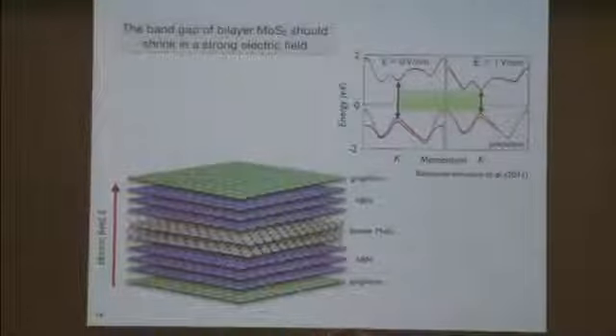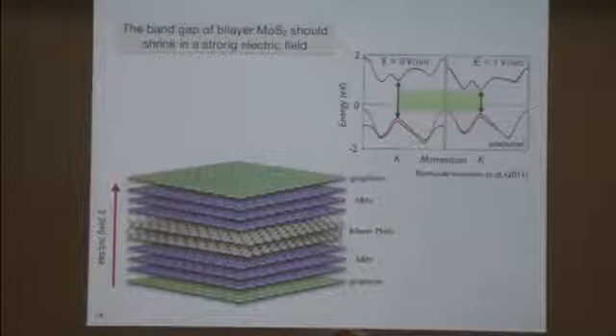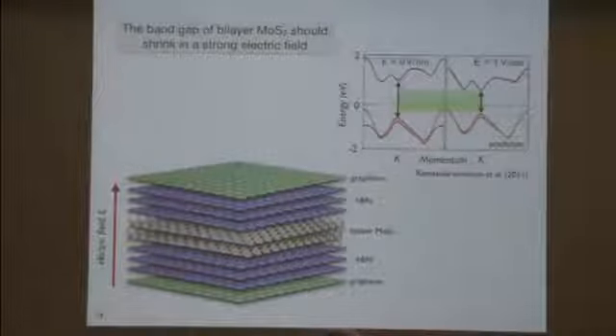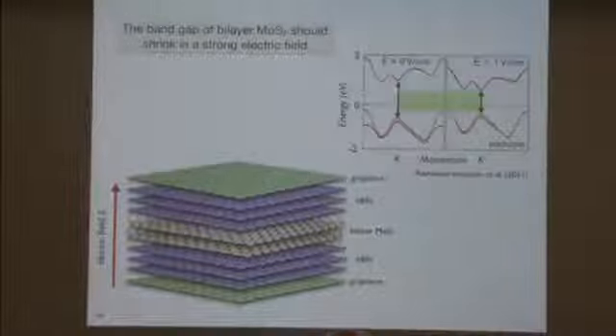So I'd like to briefly describe two other experiments that we have in mind for investigating the properties of these dichalcogenides. One is that the band gap of a bilayer of molybdenum disulfide ought to shrink dramatically in an electric field. If we make a stack of these atomically layered materials into a heterostructure like this and apply an electric field transverse to this bilayer of molybdenum disulfide in the middle, with an electric field as large as we can make before the device breaks down, we ought to be able to substantially reduce the size of this band gap, for example, by half an electron volt or so.